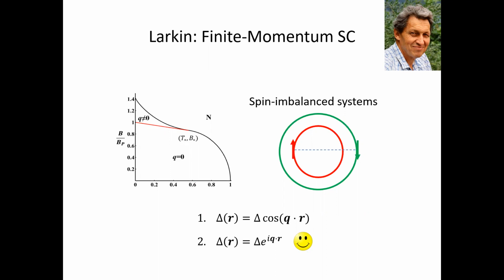Since the theoretical work of Larkin, there has been an enormous body of literature, theoretical and experimental, devoted to this subject. I won't be able to do justice to all, but let me just briefly say that there are two types of finite momentum pairing. In one case, you would take a superposition between pairing at the momentum q and minus q. And in this case, the pairing order parameter has a spatial modulation in its magnitude, but it's still time reversal invariant. Okay, so this preserves inversion and time reversal symmetry. There will be no diode effect.